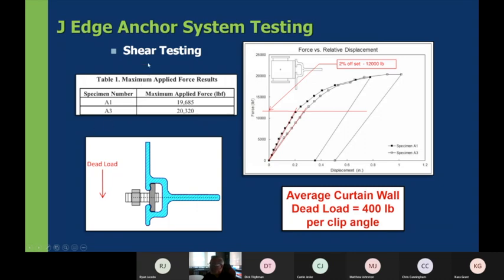In addition to that, shear testing was performed. We were able to get up to about 20,000 pounds on average with this shear testing, and that creates about a 2% offset. We can see where it started yielding above the 12,000 pound line. Our dead loads for a typical curtain wall would be about 400 pounds per clip angle, which is way down here in the bottom part of this area, well beneath what the testing came out at.